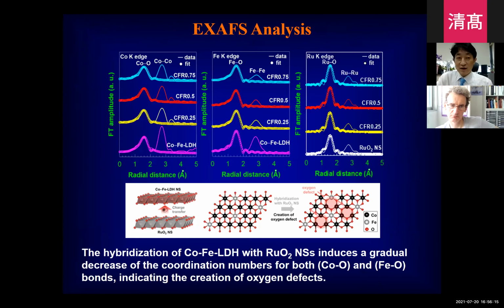Also, we used XAS analysis to prove the local structural variation during the hybridization. From the XAS analysis, we found that defect formation occurs predominantly in the LDH, not in ruthenium oxide. I believe this is related to the lower lattice energy of the LDH, because in the LDH lattice the hydroxide ligand is monovalent, and the metal oxidation state is relatively lower than in the metal oxide nanosheet. So due to such a lower lattice energy of the LDH during the hybridization, we can induce oxygen defects in the LDH lattice.